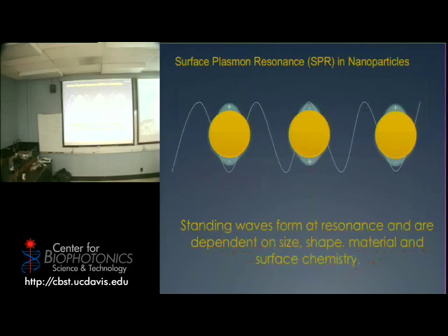So you get this thing called surface plasmon resonance. Imagine hitting a material that has been confined to a size smaller than the electron mean free path with an electromagnetic field, say light. Light is essentially an electric field that is moving up and down, and you have these electrons that try to align with it, right? So say here the field is positive, so the electrons want to go there, so one side of the particle becomes negative and the other one positive, and they go back and forth. But say the free path is 50 nanometers and the particle is 20, they cannot move that much.